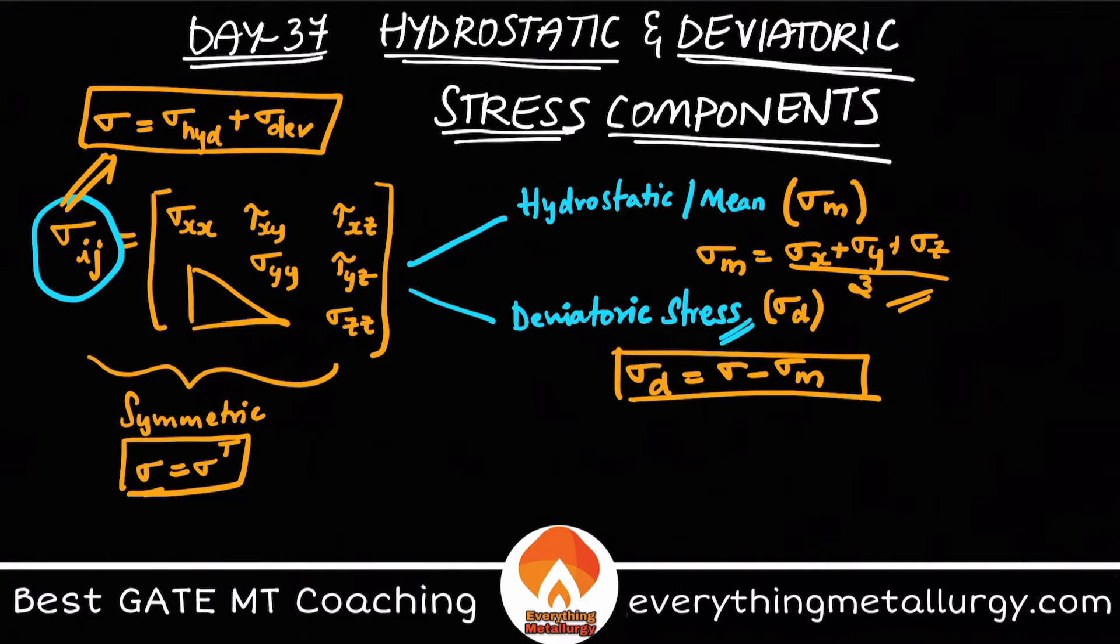Why split this? Each of these components have some particular function. Basically, my hydrostatic stress is taking care of the volume change, whereas my deviatoric stress usually takes care of the shape change. This is the main reason why we usually try to split our components.